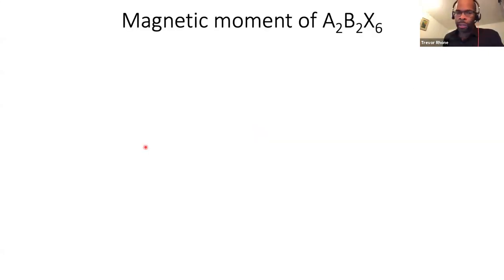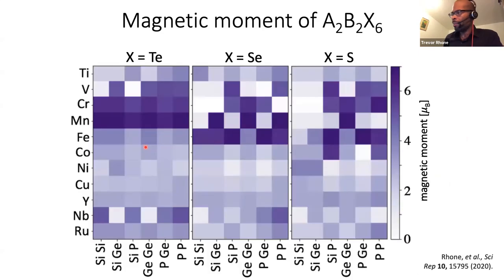Another thing we're interested in is the magnetic moment. So we can make a plot of magnetic moment versus crystal structure. And again, we have tellurium, selenium, and sulfur containing ABX structures with the A-site substitution on the vertical axis and the B-site substitutions on the horizontal axis. And the color now is magnetic moment. And there's this pattern that arises in the magnetic moment that we're hoping to extract with a machine learning model and use that model to make quantitative predictions.